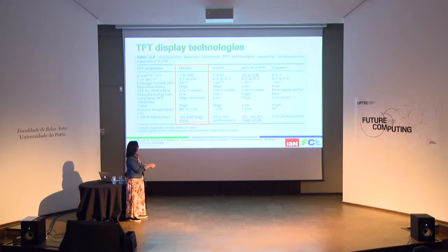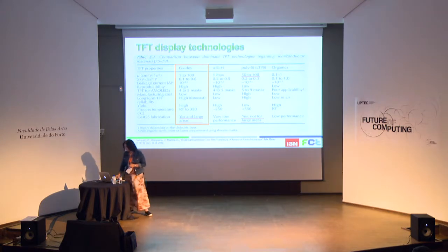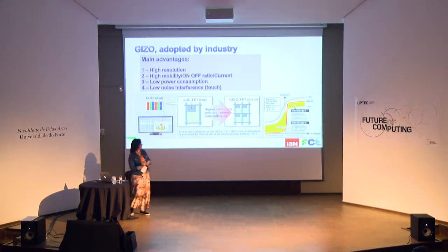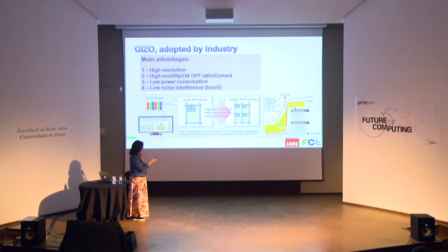And again, the organics are performing well for some applications, but in terms of the application for TFTs for the display area, also the mobility is quite low. For example, the maximum values are quite similar to the ones of amorphous silicon. And also, today, the material that is already adopted by the industry is based on this IGZO, gallium oxide, indium oxide, and zinc oxide.